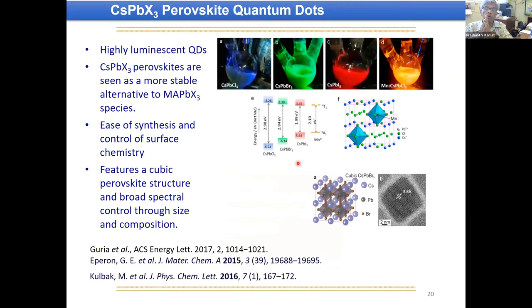So what we moved to was then perovskite quantum dots. These are mostly cesium lead halide type semiconductor nanostructures. As you can see, by changing the halides, chloride, bromide, iodide, you can change the emission, which means the band gap, you can tune it. And not only that, by mixing two halides, you can control the band gap between these two. If you dope with manganese, you can further downshift this emission.